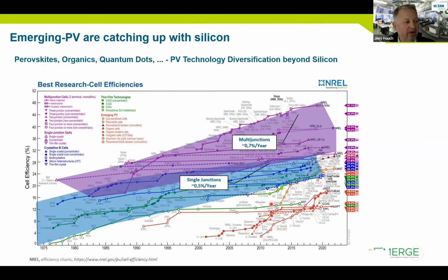Below that, we have the so-called single junctions. The single junctions are the types of photovoltaic modules that you are mostly used to seeing out there. What you see in silicon is usually all single junction technology, and this is the driver for this market. These have been developing at roughly 0.5% per year. And actually, the most important point is that they are hitting the technological efficiency limit, which is a thermodynamic limit as to how much power you can generate in a single junction with the band gap of silicon, before thermalization energy will stop you. And so this has been developing at 0.5%.